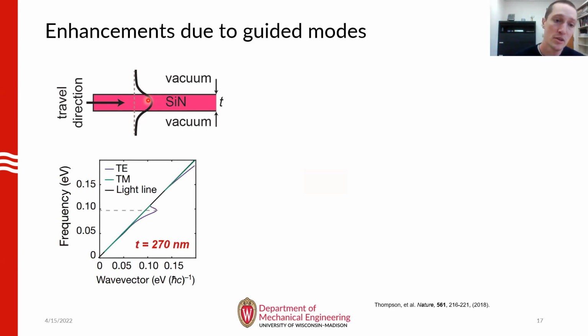So below, you can see the computed dispersion relation for the guided mode supported in a 270 nanometer thick silicon nitride slab. Here you can see that one branch of the TE and one branch of the TM modes is supported. If you look closely, you'll see that for the TE branch, the dispersion relation becomes highly dispersive close to a frequency of 0.1 electron volts, which corresponds to a wavelength of around 12 micron. So this indicates that there's a higher density of these guided modes near that wavelength.